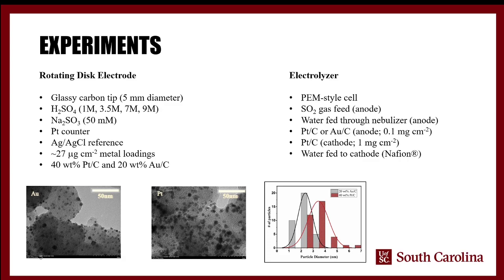of the electrolyzer. So we had 2 choices in terms of how to introduce sulfur dioxide to this rotating disc electrode experiment. One way would be to saturate the solution with sulfur dioxide by bubbling sulfur dioxide through this acid solution. The other was to use an analog, in this case sodium sulfite, and that's what we chose to go with because when you have sulfur dioxide in water, it almost immediately forms sulfite anyway, and this way we could very easily and very consistently and repeatably define the known concentration of sulfite in solution, instead of having to worry about where the equilibrium centered, how that changed with acid concentration, because it would. And so this let us know every single time exactly how much sulfite was present.